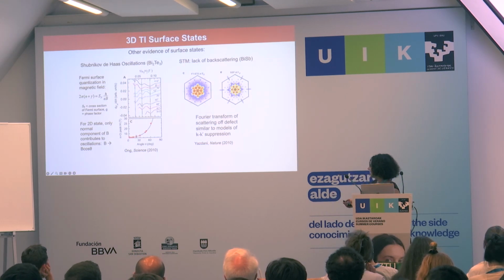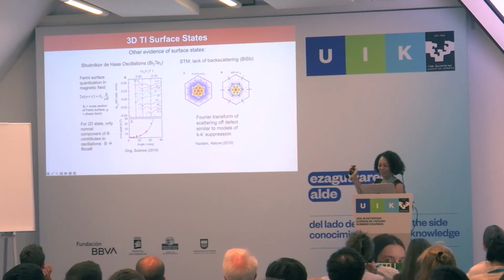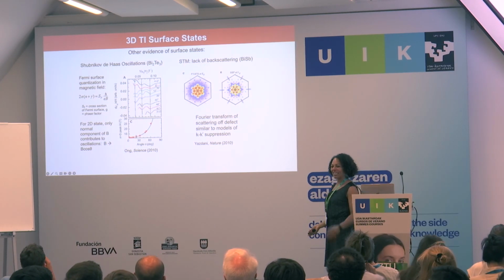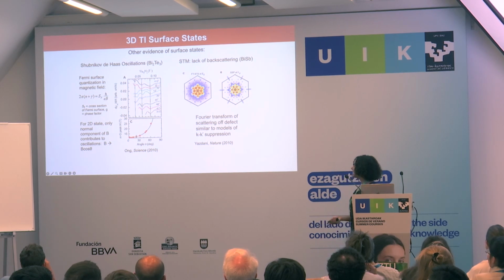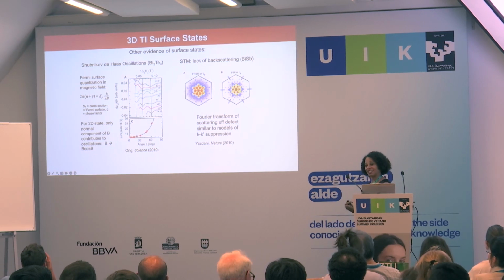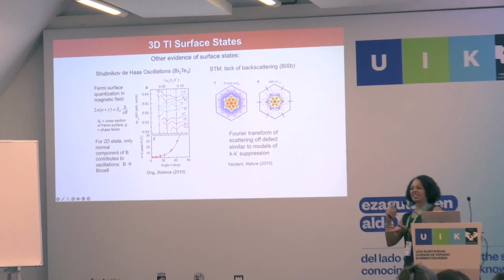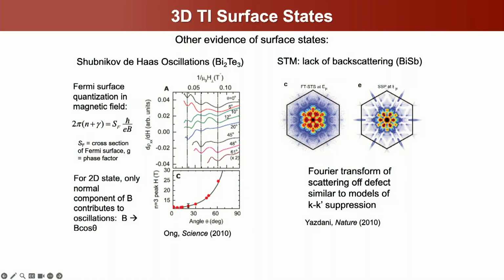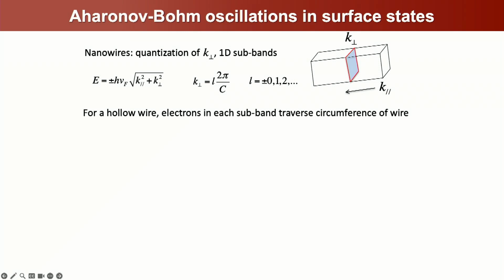I don't need to say anything about this because you heard all about these already, and we have some of the world's experts here, but one of the great ways of seeing that you have surface states is to see if you have quantum oscillations, which should change as a function of angle of magnetic field. As the magnetic field is rotated out of plane versus in plane, you can see 2D oscillations and prove that you have a 2D system that way. You can also do STM. This isn't transport, but it's a way of showing things like lack of backscattering on the surface. I'll mention a little bit more about one of the experiments we did to determine some of the surface properties, which is looking at Aharonov-Bohm oscillations in this sort of nanowire surface states.